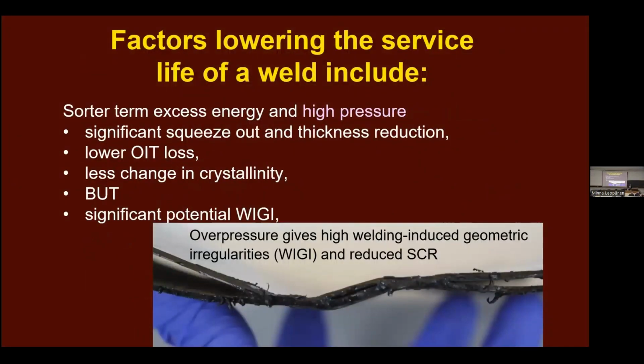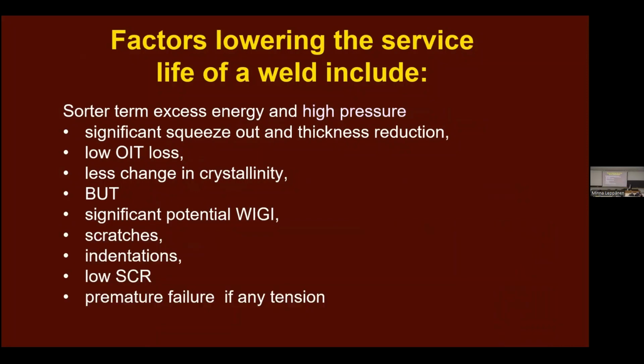Also, if you apply too much pressure, you get something that looks like this. It looks like a mess. It is a mess. It passes all the strength tests and it will fail very quickly. Other things that damage are scratches, indentations, and the result is low stress crack resistance and premature failure.